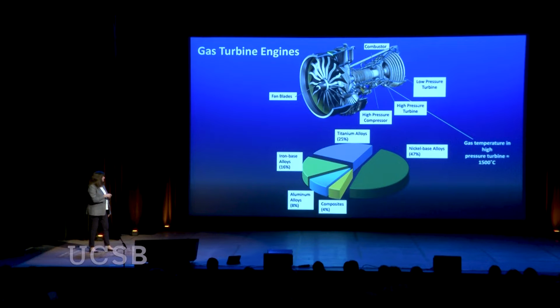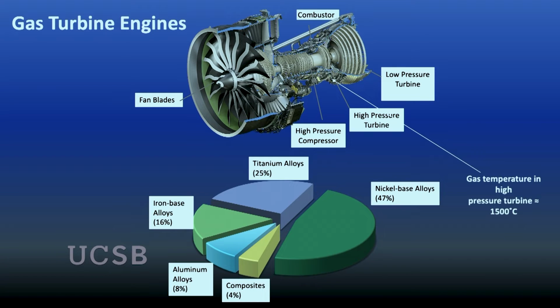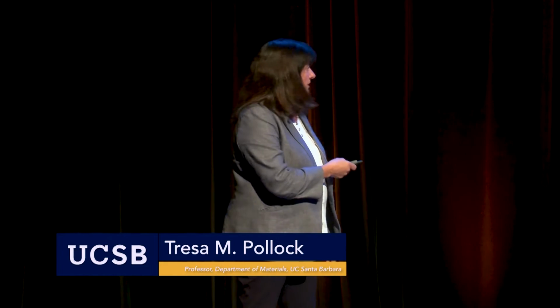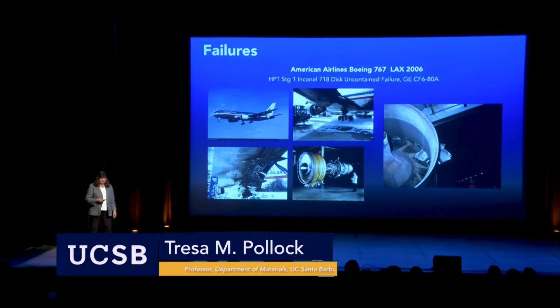Now, looking at the materials of construction from the front toward the back, we start with composites or maybe aluminum alloys in the fan. This has to resist bird strikes. That's one of the critical tests for an aircraft engine. You throw a frozen chicken in the front and that fan blade cannot break. Then we go on back and we have titanium alloys, mostly in the compressor. Then we combust, and then almost everything behind that is composed of nickel alloys. The progression here is basically that they have increasing melting temperatures, and so you get hotter and hotter as you go toward this high pressure turbine.